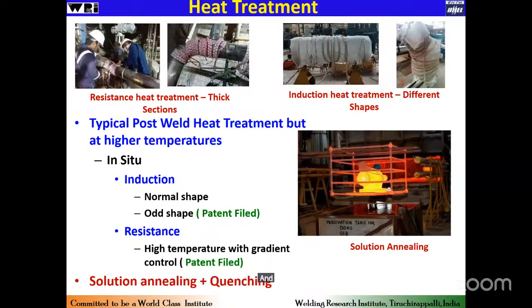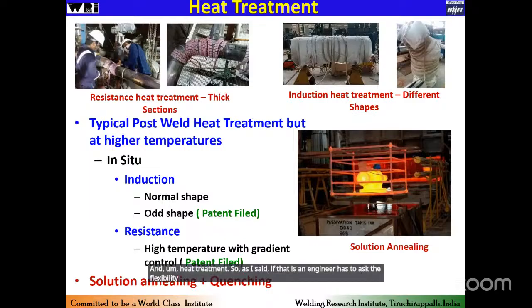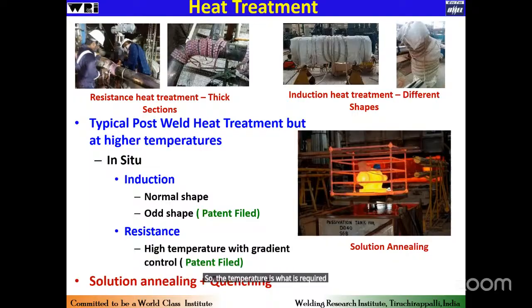And heat treatment. So as I said, if the design engineer asks for flexibility, then the component shapes can be odd as well. And especially when we talk about these kinds of nickel based superalloys, the heat treatment temperatures are also going to be different, so that we have seen the dissimilar welding as well. So the temperature required for the nickel based superalloy is around 900 to 950 degrees centigrade, and in certain cases we may have to go for solution annealing in excess of 1100 degrees centigrade.